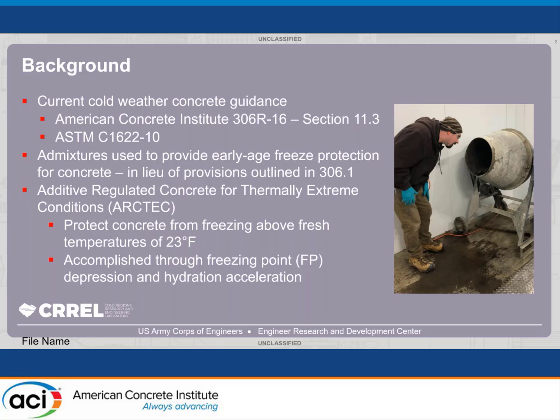And this has been done for a long time, and it started because there wasn't really any guidance that existed that said you could do that. All the guidance says if it's below 40 degrees, you really need to incorporate a tent, heating it up, and so researchers at CRREL tried to find another way to place concrete in freezing temperatures.